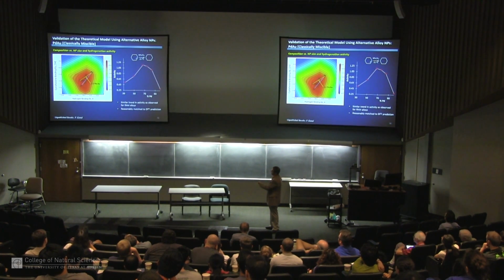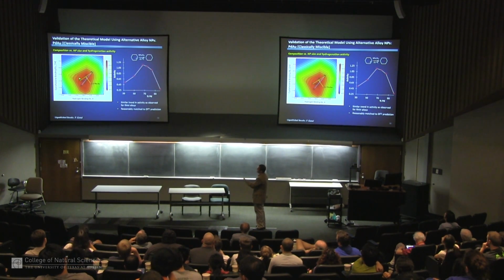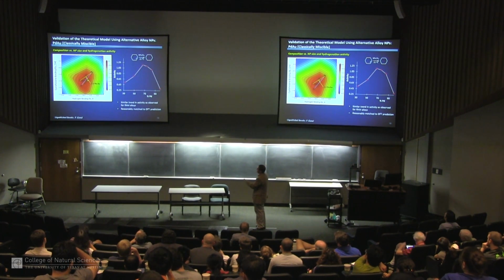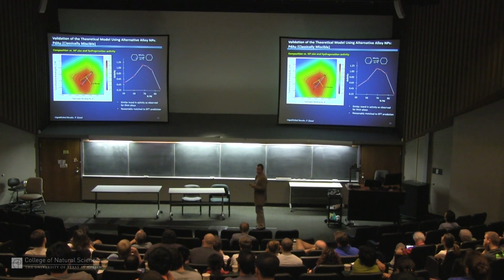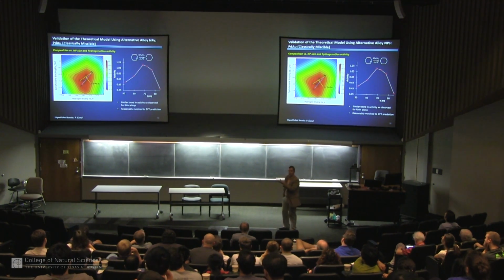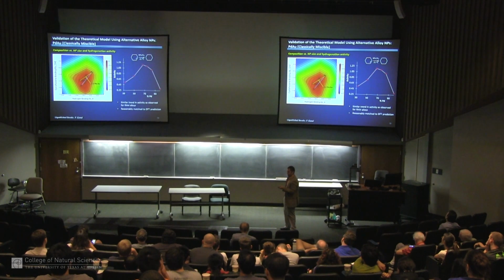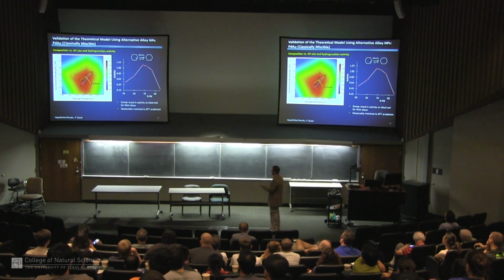What Graham hasn't seen is that we've started to try and probe this with other alloys we can make. Here's a palladium gold alloy, so we've put a new line on the diagram. And again, it correlates pretty closely. We see that about 70% palladium is the most active. This is work by Prano in my group. And that does get pretty close to the center of the line. So we've got a lot to do with this now. We've got some money to work on this. We can make alloys with 3 or more metals in the structure, and we can dilute expensive metals and make more active catalysts, which is good.